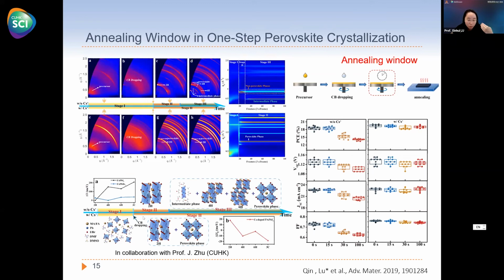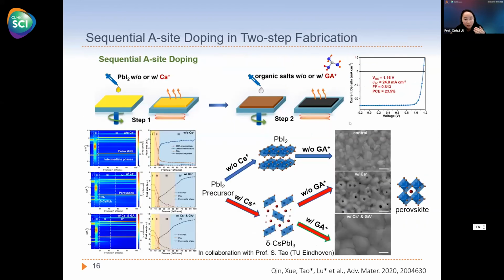But with cesium, the stage 2 is elongated quite a lot, and the reproducibility of our device increases significantly. Then we try to understand the 2-step fabrication technique. For this, we can do A-site doping both in the first step and in the second step. In the first step, without cesium, it starts with lead iodide, but with cesium, it forms some